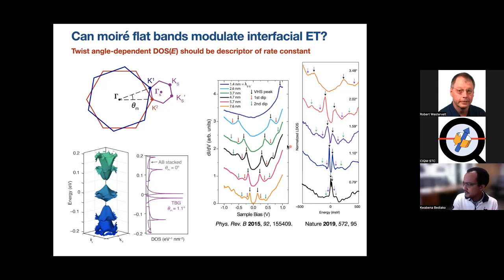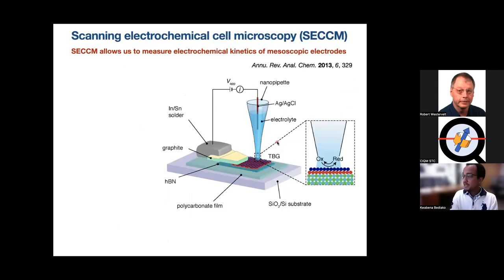But atomic defects and steps and things like that are notoriously difficult to control chemically. So we wondered if these flat bands could be used as a more controllable way to modulate interfacial charge transfer at surfaces. So we went ahead and did that experiment. It took us a while to figure out how to make the samples and the way we needed to make them to be able to do the experiment, and then also to be able to reliably take these measurements,